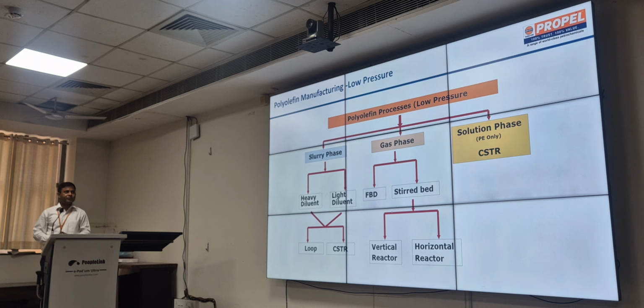For low pressure processes, we can differentiate the different processes like slurry, gas phase and solution process. In slurry, there is heavy diluent or light diluent; gas phase uses fluidized bed reactors and stirred bed. Slurry can further be loop or CSTR based on the reactor, vertical or horizontal reactor systems. Basically, through the catalyst and the different reactor systems, you can decide the molecular weight distributions. You can use different reactors in series or in parallel to get different molecular weights in different reactors, and then you can have a broader molecular weight distribution, so bimodal or multimodal can be produced.